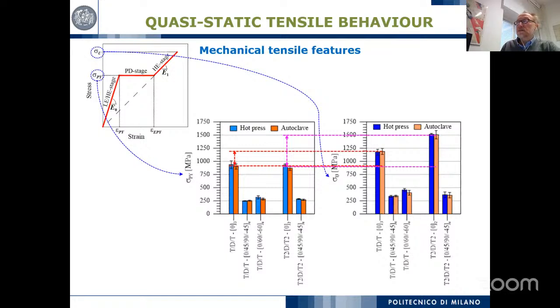And this is also visible when we compare the stress at the pseudoductility level, or when this pseudoductility starts, and the final strength of the material. This also shows us that by changing the quantity, the position and the orientation of the different carbon ply, you can create a smaller or larger gap between the two values. This is very interesting in the application, because when you are in this pseudoductility range you have further space for increasing the load, and so you can know exactly where your material is working.